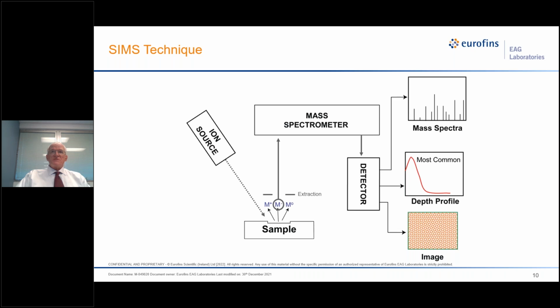And we can display the data in three different ways. A mass spectrum, which for reasons I'll explain in a bit, is not used very often. An ion image there at the bottom, we can get a mass-specific XY image of the sample surface. But the most common is to do a depth profile. We follow one or more elements of interest as the sputtering proceeds. And since as the sputtering proceeds, the surface recedes into the bulk, if you plot the intensity versus sputtering time, you will get a depth profile. That's the really basics of SIMS. Everything else is, I won't say window dressing, but it's where the complications set in.